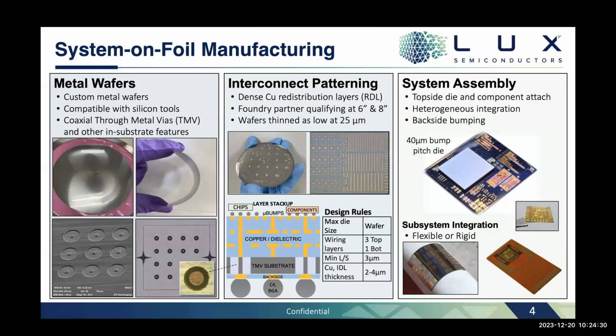Wait, so I don't understand something basic. Every time I hear this, I thought you have a metal thing, won't it just be conducting signals where it's not supposed to? Yeah, that's a good question. So if you look at this cross section here, this is the bare metal wafer, and then we pattern the metal wafer. Here we're just showing through metal vias. This darkness here is filled, it has dielectric in it. So this metal pin is electrically isolated from the surrounding metal all the way through the thickness, and that's shown here.